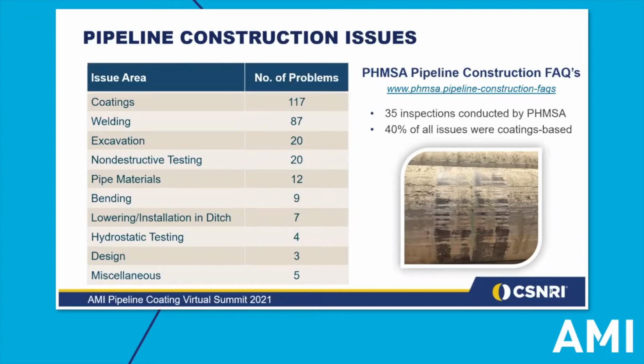Before we look at possible ways, let's review a snapshot of PHMSA's FAQs on pipeline construction. This was based on 35 inspections conducted by PHMSA. This shows coatings are the leading issue found during pipeline inspection. Some of the most common coating concerns that inspectors noted were heat damage to FBE, coating over mud or rust, girth weld coating not fully bonded to the pipe, applying epoxy above or below the manufacturer recommended temperatures, and of course, the age-old issue of surface preparation. All of these scenarios can and usually do result in corrosion. If these 35 inspections were done prior to the trenchless installation occurring, how much more damage might we find if post-construction were able to be inspected in the same manner?